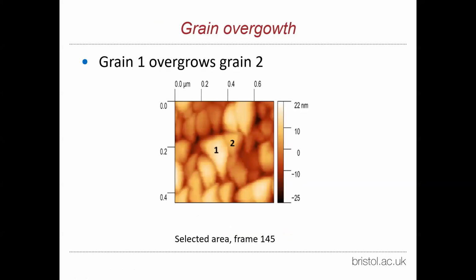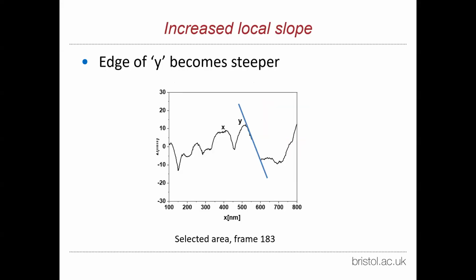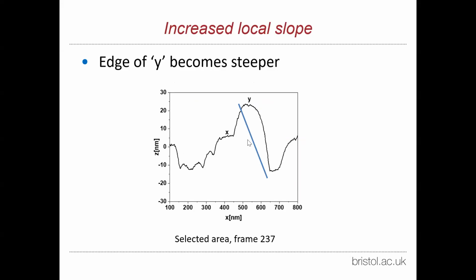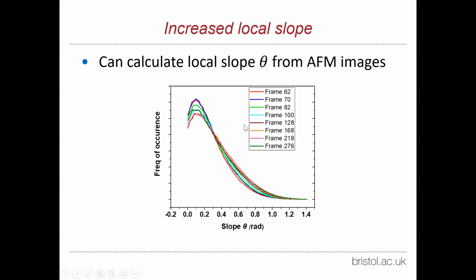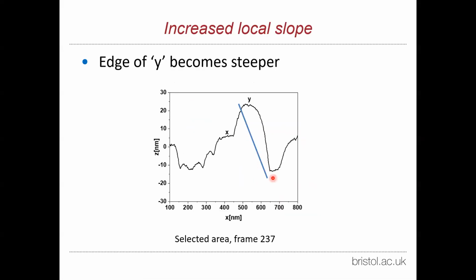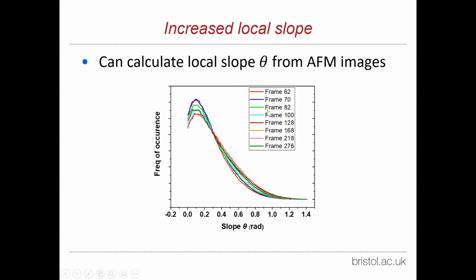Here you see another two grains, grain 1 and grain 2. You can see that grain 1 grows over the top of grain 2. Going back here, grain 2 almost disappears underneath grain 1. So you can also see from the cross section that the slope increases. The original slope is the blue line, and the new slope is more vertical like this. You can also measure the slope across the whole sample, and you can see that the mean slope is actually increasing as you do so.